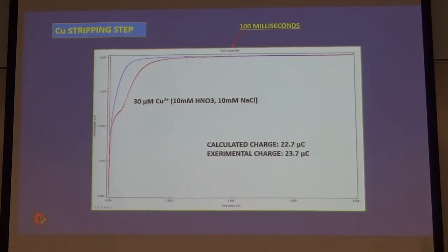Whenever you jump the potential, the electrode has to charge up to the new potential value. That's called charging current. That's very fast normally, and that's what the blue trace is. If we then do the same experiment, add some copper to the solution, and we reduce it, we deposit it, then we strip it off, we get this signal here, the red one. This is a fairly high copper concentration, but you can see that signal is back to the background within 100 milliseconds or so. So the stripping step is very, very fast.